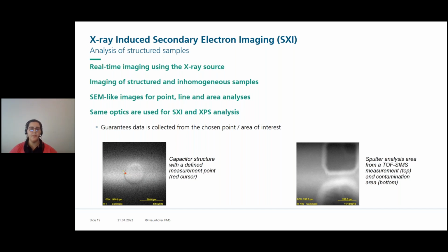And since we use the same optics for SXI and XPS analysis, this really guarantees that the data is collected from the chosen point and area of interest. So at the bottom here, we have, for example, on the left, a capacitor structure with a defined measurement point as the red cursor that you see.